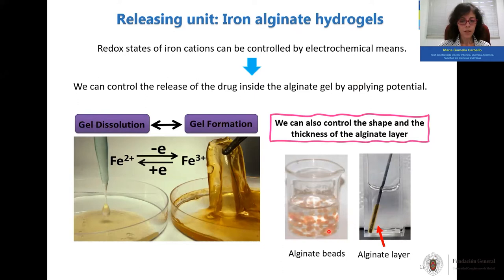And it's very important because of that, we can control the amount of drug that we want to release. It's very easy to prepare the beads, as I have already said. You just need to prepare the solution of alginate and add iron plus 3, and these beads are going to appear. But what happens if we prepare a solution of alginate in the presence of iron plus 2? The solution is still not gelified. But if we introduce an electrode and apply a positive potential in order to oxidize this iron plus 2, an alginate layer is going to form on the surface of the electrode. Therefore, depending on the shape of the electrode, we can control the shape of the alginate layer. Additionally, since we can control the time during which we apply the potential, we can control the thickness of the layer.